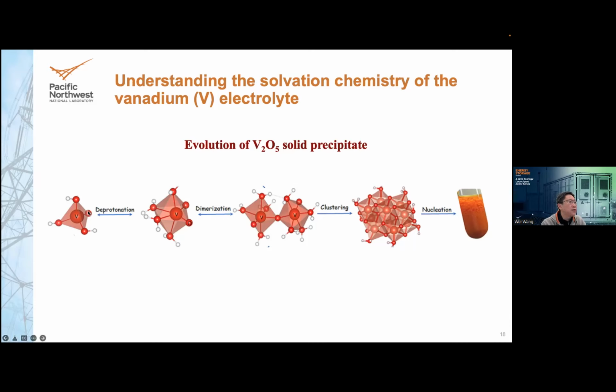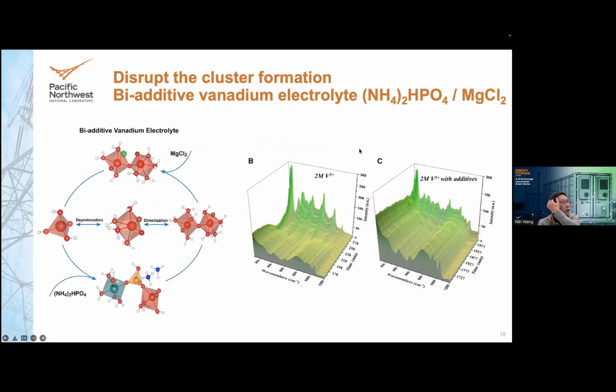I talked about this deprotonation process and how to prevent it. Furthermore, if we can prevent the clustering after the dimerization and polymerization, then we can also stabilize it. That can be done with these bi-additives, the magnesium and the phosphate salt. The mechanism is very complicated, but in general some of the anions and cations form hydrogen bonds or non-covalent bonds with the vanadium 5 species, and in that way effectively separate them further apart and prevent them